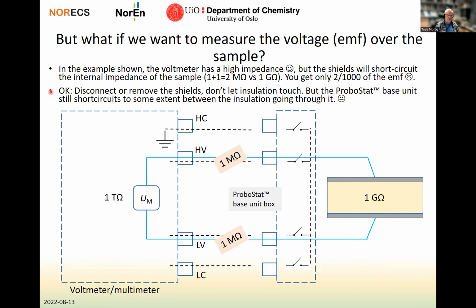Because if you now move on to measure the voltage, the situation is different. Here I have now shown a voltmeter or a multimeter with some terminals. The important terminals are now only the voltage terminals where we measure the voltage. And let's say that this internal resistance of this voltmeter is 1 tera ohm. So it is in principle very well suited to measure the voltage over this sample of 1 gigaohm without causing much error because there's very little current running here. But as we have said already, the shields can be a problem. If these shields for some reason now are connected together via the shields bridge or quite simply lying next to each other, touching each other, they easily short circuit these two wires via the shields.